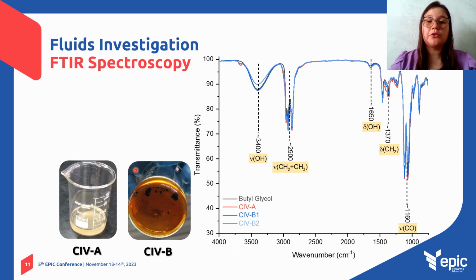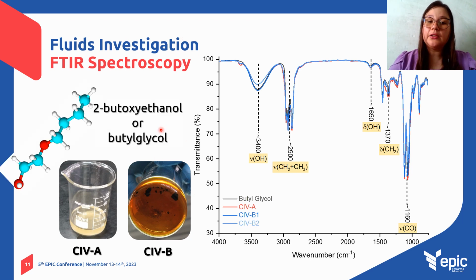Here is the spectroscopy investigation of the fluids collected inside the chemical injection valves A and B, whose infrared evaluation demonstrated an infrared pattern compatible with 2-butoxyethanol or butylglycol, indicating to us that the butylglycol is used to flush the chemical injection line and to prevent hydrate formation at the emulsifier injection at the Peregrine basin.